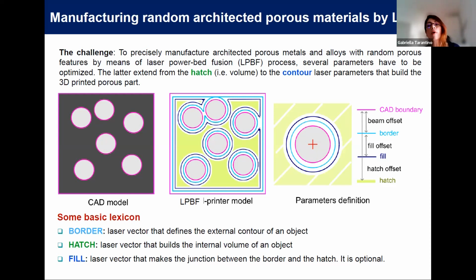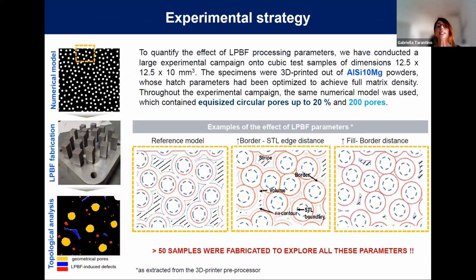A basic lexicon before I walk you through the results of this work is that we have to consider parameters which imply, for example, other vector definitions, like the border, and how we make the junction between the volume and the border. You can see from this basic sketch that the impact of this parameter is actually pretty huge. And to be honest with you, we were not aware of how much these parameters are really relevant in the proper fabrication of this microstructure.